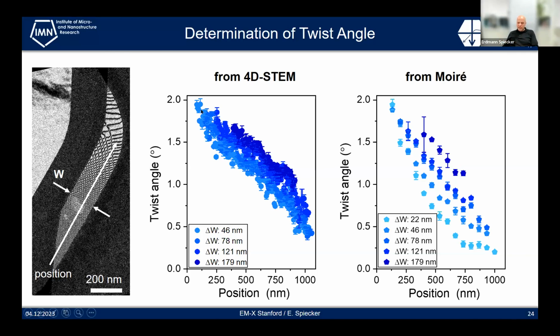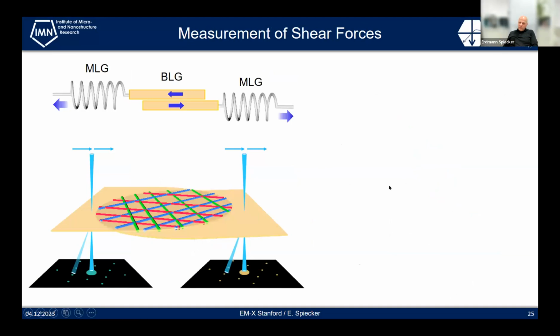But you see now the twist angle is very consistent, independent of whether you measure it with 4D STEM or with a mesh size from the moiré. Now, maybe even more important, because the twist angle is pretty easy to measure, is how can we measure shear forces? And the idea here was that we use a monolayer graphene as a kind of spring. So we know the elastic constant of monolayer graphene, and we know that we pull on monolayer graphene on one side and on the other monolayer graphene on the other side. So by measuring the strain in the monolayer graphene and using the elastic constant, we should be able to measure the force or the stress, the shear stress in the bilayer graphene. And this is shown here on the right,